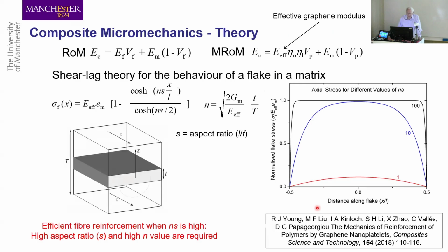The problem is that if your matrix has too low a modulus, it's not able to transfer stress from the graphene. So you can't get good stress transfer with a low modulus matrix. You get much better stress transfer with a higher modulus matrix. And this all comes out in the shear lag theory, essentially the stress in a flake as a function of its stress transfer coefficients and its geometry. It also depends on the aspect ratio of the fiber or the reinforcement. The aspect ratio is the most important thing, rather than its properties.